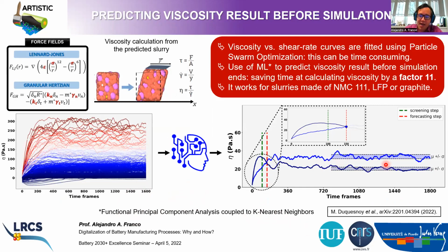In that way, as we can predict from the very early steps of the simulation, we can predict what will be the viscosity value that the simulation will be able to obtain. Then we can integrate this forecasting technique in an optimization loop that allows us to fit the experimental curves more quickly, right? And this concept, which we have published very recently as a preprint, works for slurries made of NMC 111, LFP, or graphite. Before, we needed a few days to fit a viscosity curve with one of these models. Nowadays, we need only a few hours to fit a full viscosity curve coming from experiment with this kind of model.